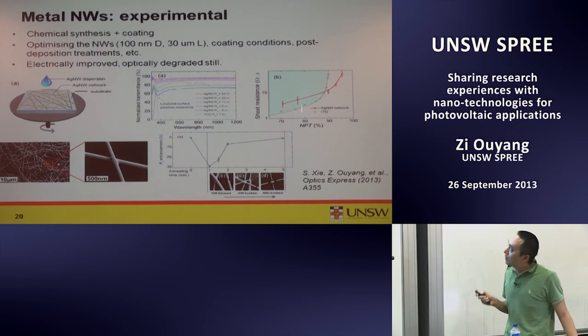So if you talk about the same resistance, it's more transparent. Or if you talk about the same transmittance, it's more conductive. So at some point. But this is very initial result, and we think, oh, what's the limit? And also we put it on solar cells, and we see efficiency enhancement, mainly due to the reduction of series resistance, as we can imagine. So when we anneal it, we actually have better connection down here, and we have sort of series resistance reduction.